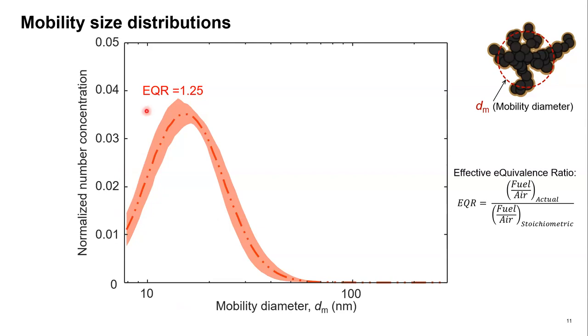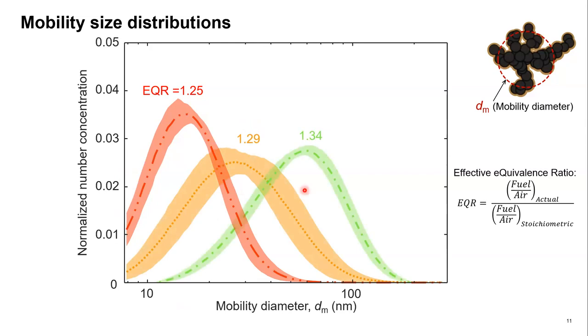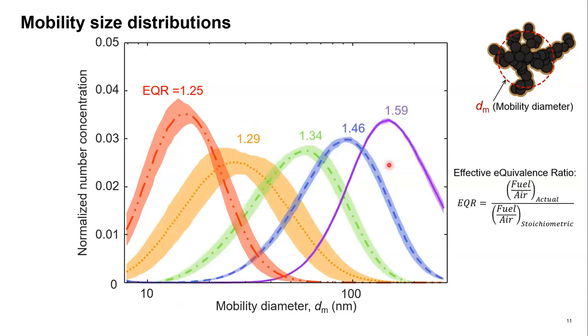So here at the leanest equivalence ratio we used, we have the smallest mobility diameter of approximately 15 nanometers at the median. Increasing the equivalence ratio slightly to 1.29, we increase the median mobility diameter up to about 30 nanometers. As we continue to go to richer and richer flames, we can see the distributions shift from left to right up to the highest equivalence ratio of 1.59, which has a mobility diameter of approximately 150 at the median, so an order of magnitude larger than the smallest one.